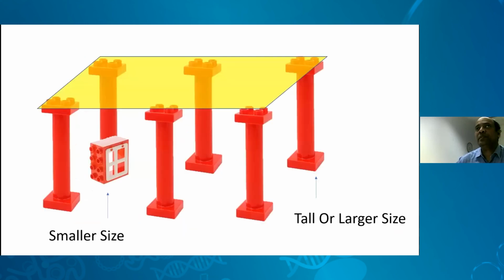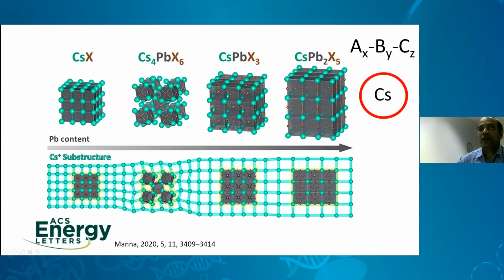So this behaves simply like a toy building. There is a roof here. For the smaller size windows, you can replace them, but the tall or larger size pillars you cannot replace. Once you replace the pillar, the building will collapse. That's the phenomenon. And here is the Liberator Manna group. They have all shown that whatever the cesium halides might be, and the compositions of lead halides with cesium, the lattice that is created with the cesium remains almost the same everywhere.